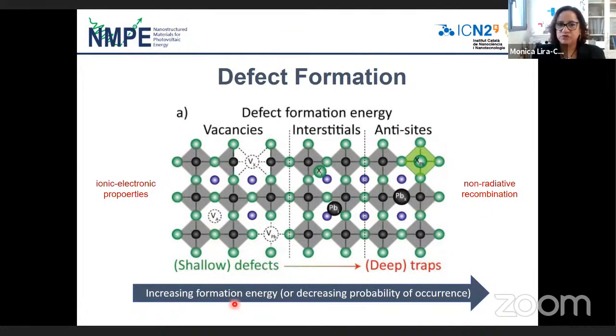However, in halide perovskites, these shallow defects are related to ionic-electronic properties. You can see here that the formation energy is low for shallow defects and very high for deep traps. So it's very easy to form these shallow defects, this ionic movement.